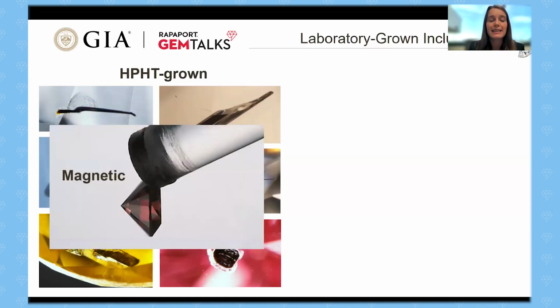Additionally, because they are metallic in nature, they are magnetic. So if you were to have, say, a parcel of lots of melee diamonds with lots of inclusions, and you passed over it with a very strong rare earth magnet, you might actually find that you're able to pick up these stones due to the magnetic nature of the metallic inclusions within them. And this is something that can be particularly helpful for small stone screening.